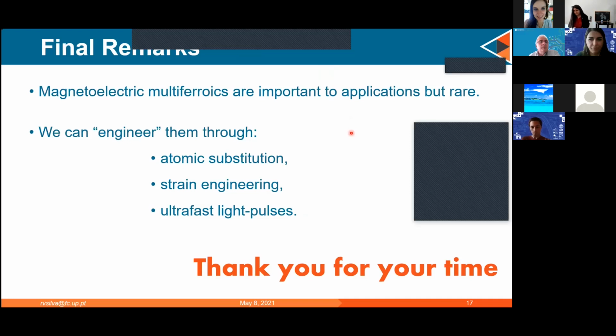Go ahead, Himanshu. The question is, what method did you use to deposit the film of GdMnO3 on the SrTiO3 substrate? It was pulsed laser deposition, so PLD. What was the thickness of the film? The thickness was around 30 nanometers. So above that, the strain relaxes and the structure becomes more bulk-like. So below 30 nanometers, you have a fully strained epitaxial film.